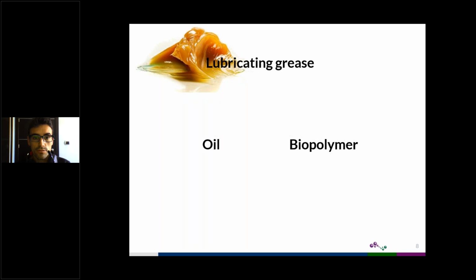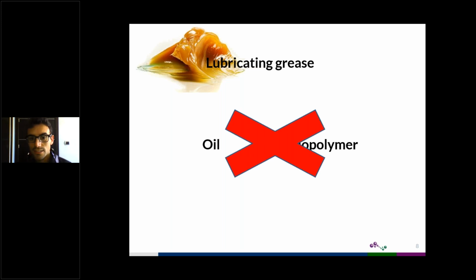Well, what about lubricating greases? Can we obtain a lubricating grease just by mixing an oil and a biopolymer? The answer, unfortunately, is no. We cannot obtain a proper grease just by mixing the oil and the biopolymer. What we get is just systems that are separated. So in recent years, we have been focused on using isocyanate and epoxy compounds to try to cross-link both the oil and the biopolymer.